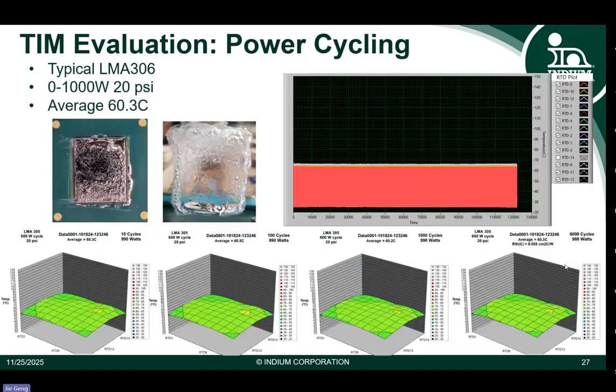Here shows a typical measurement from the TTV. This is running for the liquid metal at nearly 1,000 watts, for up to 6,000 cycles. The temperature is read from the different RTDs in the silicon chip and plotted at the different locations. So in this case, that's showing the liquid metal has very good compliance to handle the big warpage. So for this TTV, the warpage is about 125 microns.